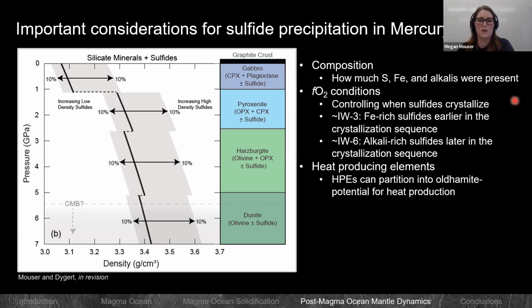Heat-producing elements are an interesting component in this, because oldhamite in particular, and niningerite as well, can hold a fair amount of these heat-producing, incompatible elements, such as uranium, thorium, and potassium, some of those long-lived radiogenic isotope systems. So if you're precipitating these sulfides, which maybe have a fair amount of these incompatible radiogenic elements, and you're crystallizing them into specific regions in the mantle, over millions of years you could introduce a fair amount of heat into the system that maybe could start some partial melting and change the rheology of some areas of the mantle, which is definitely an interesting consideration.